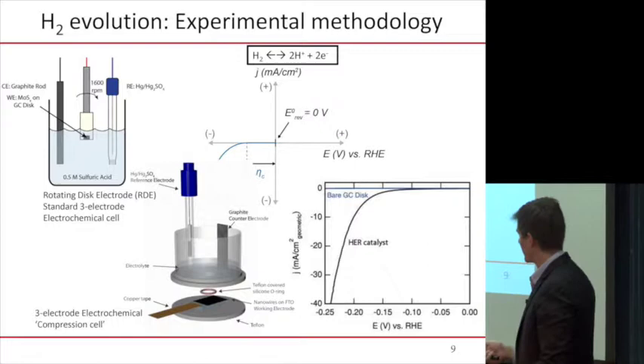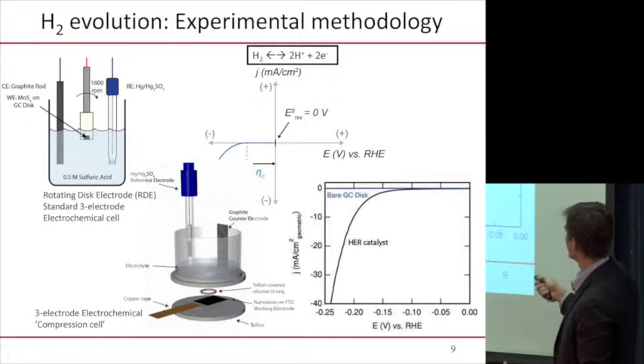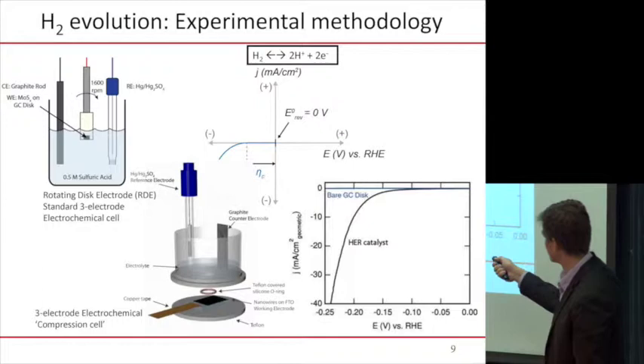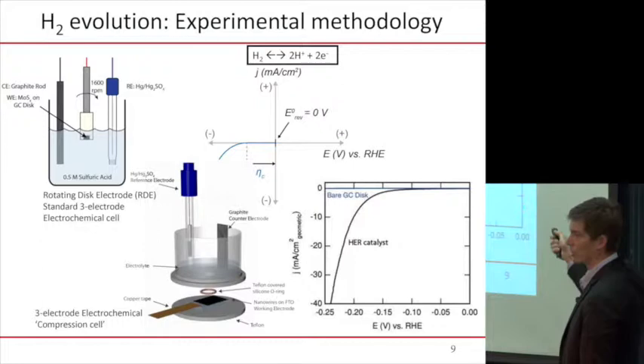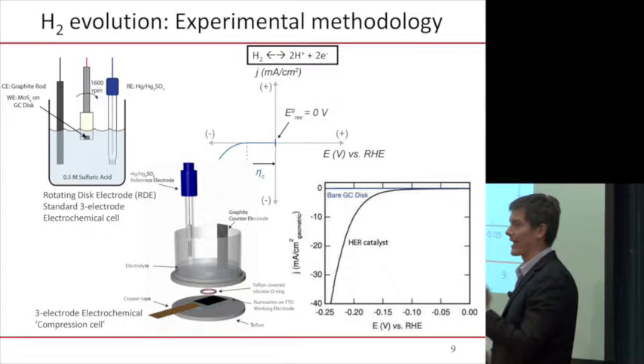So that's what the data looks like schematically. In real life, here's, again, current versus voltage. Here's with no catalyst, it's totally flat. You don't get any current out of the deal. It means no reaction is happening. In this case, when we do put a catalyst for the hydrogen evolution reaction, then you can see that you get this big negative current. And the goal is to make catalysts where this is closer and closer to zero, because zero is what's known as the equilibrium potential. You hold your electrode at zero, the forward and backward reactions are exactly the same rate, and so you get zero product.